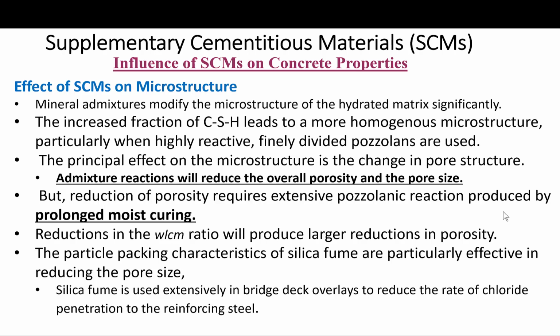The residual calcium hydroxide crystals are usually smaller and can have altered morphology. The principal effect on the microstructure is the change in pore structure. Admixture reactions will reduce the overall porosity because the specific gravity of calcium silicate hydrate is lower than that of calcium hydroxide, and they will also reduce the pore size, not just the overall porosity.